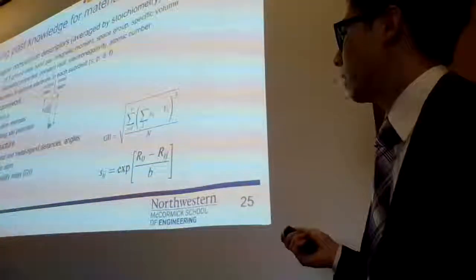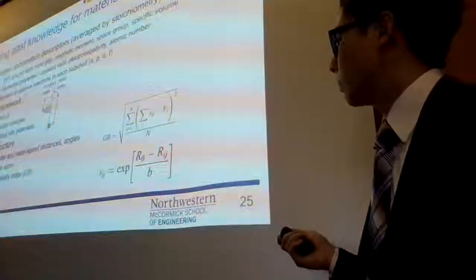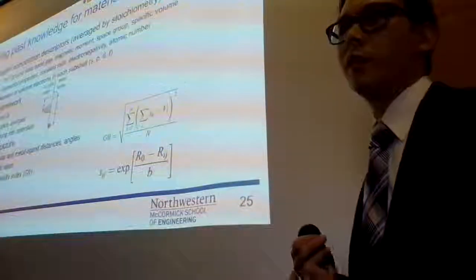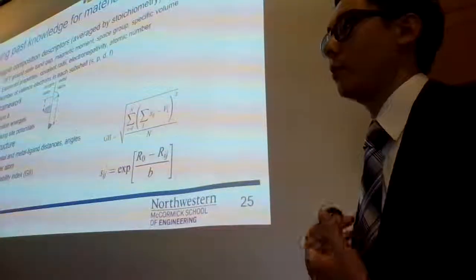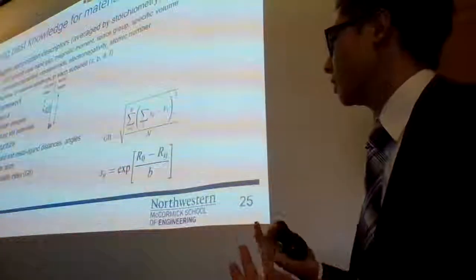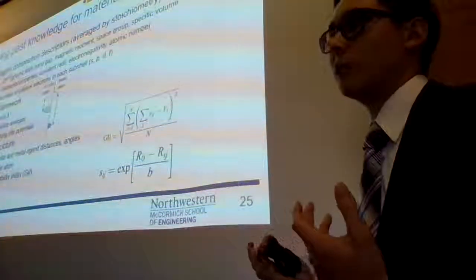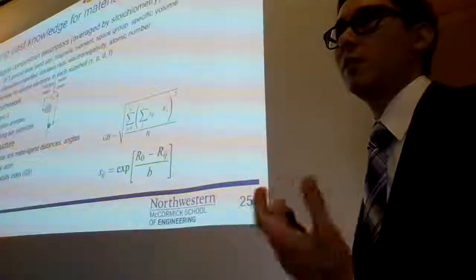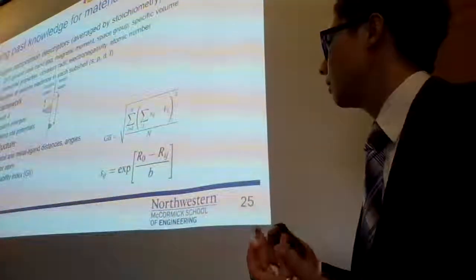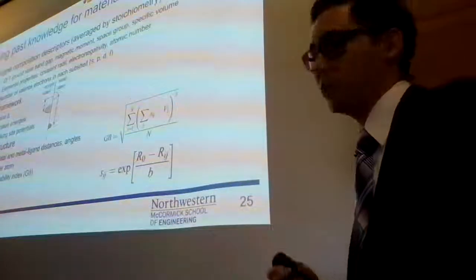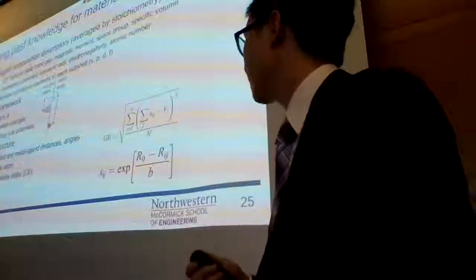So these R_ij parameters are the actual bond lengths, and then R naught are known bond lengths from, say, a crystallographic database. It's essentially an estimate of how much your bonds deviate from what you would expect given this normal bond found in the inorganic crystal structure database.